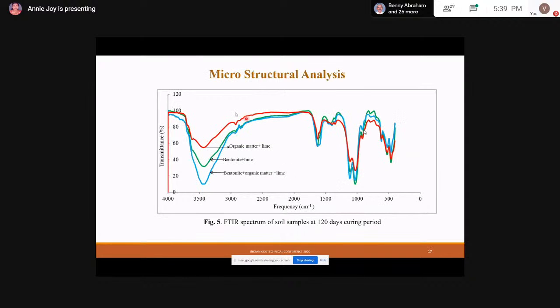Now, in order to confirm the above results, we conducted microstructural analysis. For the present study, we have conducted FTIR spectrum analysis. And from this figure, you could clearly see that for any particular frequency, the transmittance goes on increasing with the increasing organic matter content. The reason behind this is that with the addition of organic matter, there is an increase in pore size due to the aggregation, and this increase in pore size confirms the results that the compressibility increases and the UCS or the unconfined compressive strength of the soil sample decreases with the increase in curing period.